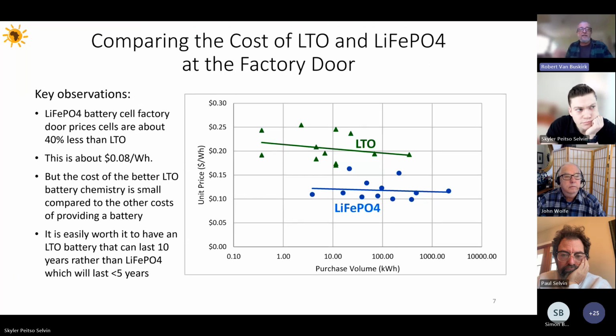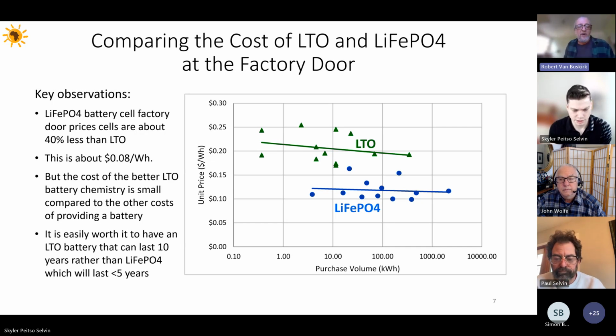Oh, right. And then here's the slide that shows the per watt hour cost of the battery cells when you buy them from the factory door in China. What happens is the per watt hour cost of the lithium iron phosphate is about 12 cents per watt hour. The per watt hour cost of the lithium titanate is running at about 20 cents per watt hour. So the difference between the lithium titanate and the lithium iron phosphate is about 8 cents per watt hour right now, which means that because there are so many other costs to building the battery, the extra cost of the lithium titanate isn't necessarily that big, right? It's about 8 cents per watt hour.